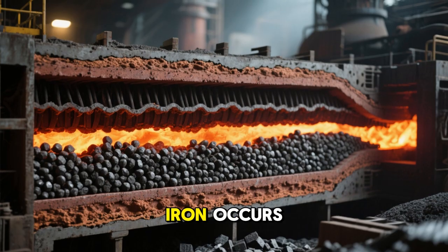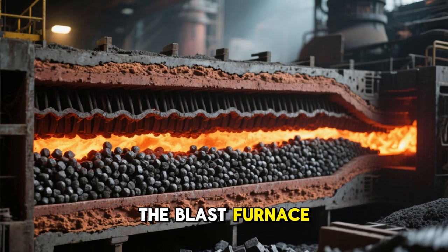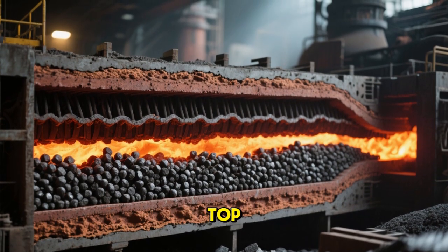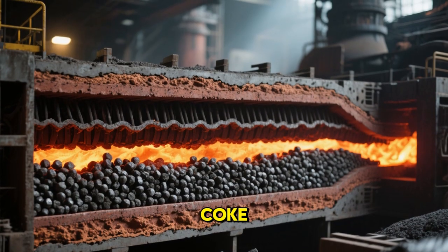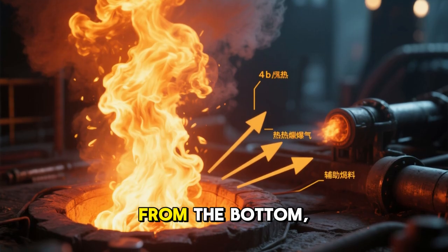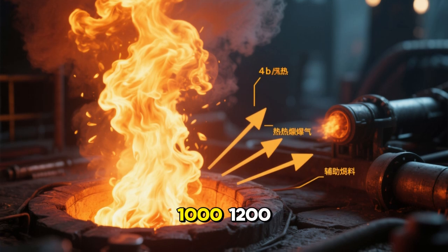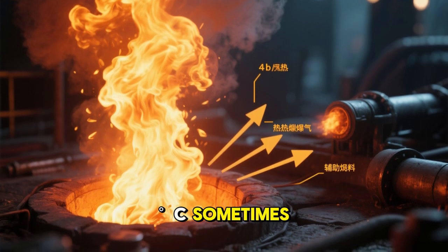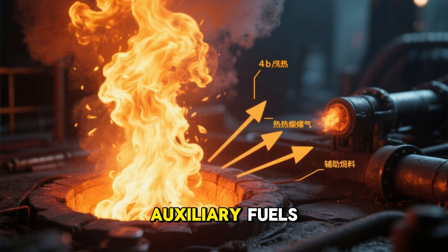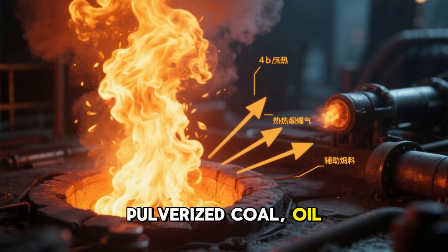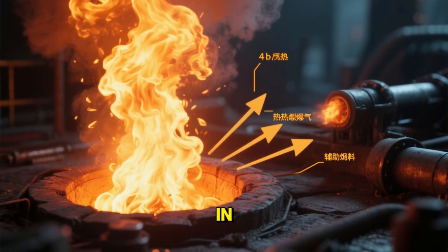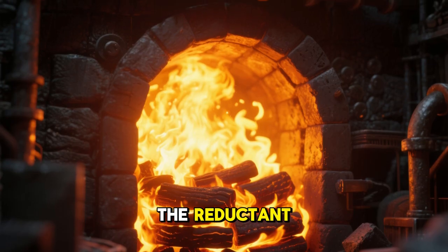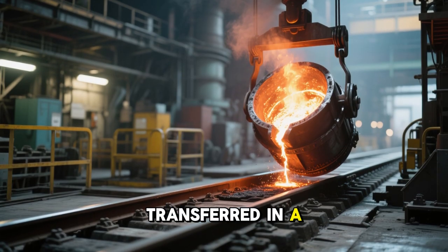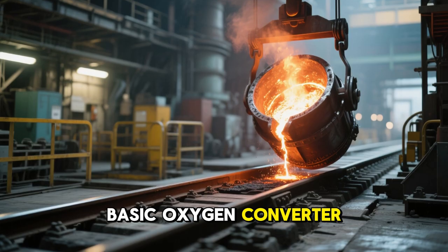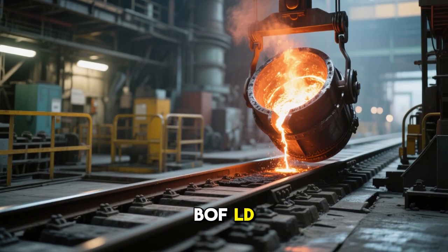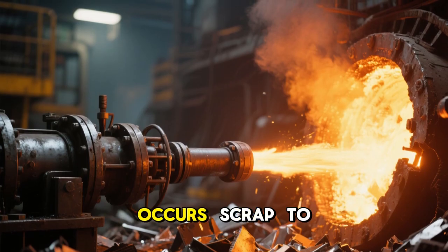Ore reduction to iron occurs in the blast furnace. The blast furnace is a counter-current reactor. From the top, alternating layers of sinter, pellet, coke, and fluxes are charged. From the bottom, hot blast air at 1,200 degrees C, sometimes oxygen enriched with injected auxiliary fuels, pulverized coal, oil, gas, is blown in. Coke supplies heat and CO as the reductant. The hot metal is transferred in a torpedo ladle to the basic oxygen converter, BOF-LD. Here, primary decarburization occurs.